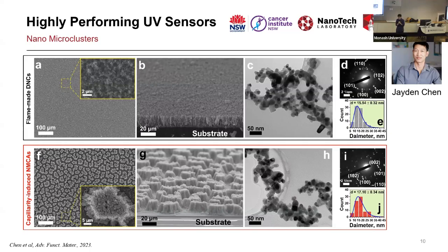Maybe I can add a point about that cold welding process, because in the field of ceramics, I've done a bit of piezoelectric ceramics. There's a process called cold sintering, which involves mixing particles with a minute amount of acids. By cold sintering, they mean sintering at low temperature, like 200, 300 degrees versus 1,200 degrees. That acid helps with dissolving the surface of the particles, and then facilitates diffusion, and later welding when the whole thing dries. I think that's why when you use acetic acid droplets, that facilitates a similar process.